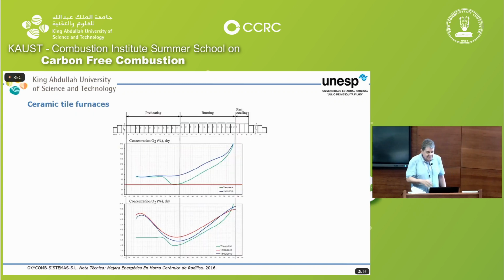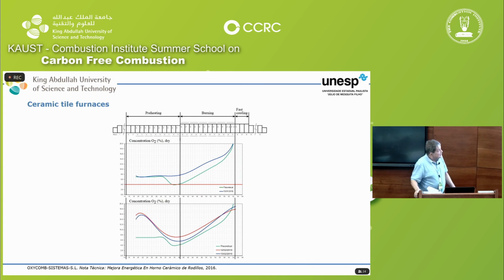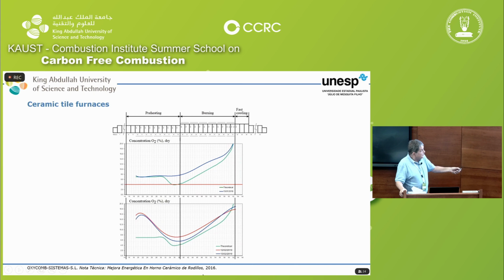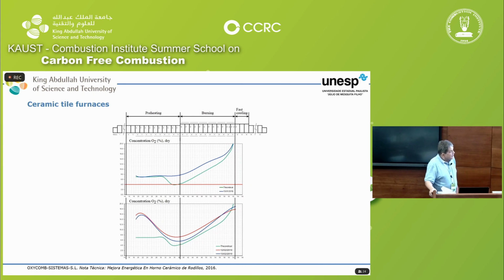So what happens if you do the substitution in there? These tiles have something which is very important. The oxygen atmosphere: you see they have a bunch of burners, and they have a temperature profile that I'm not showing here. But they have an oxygen concentration profile that cannot go below 4%. Cannot go below 4%. And for economy, it is advised that you should be as close as possible to the theoretical value that is recommended by this publication here. So we did the work in there with the air.